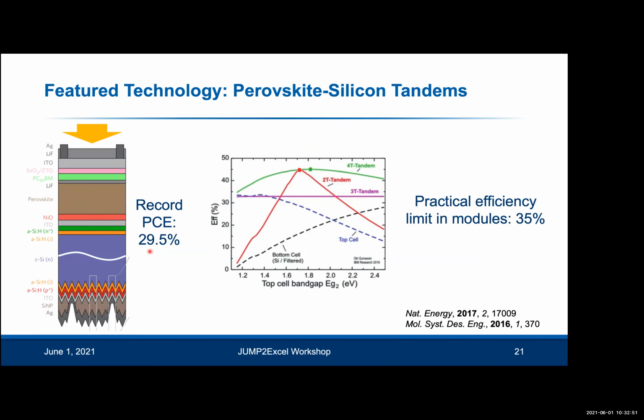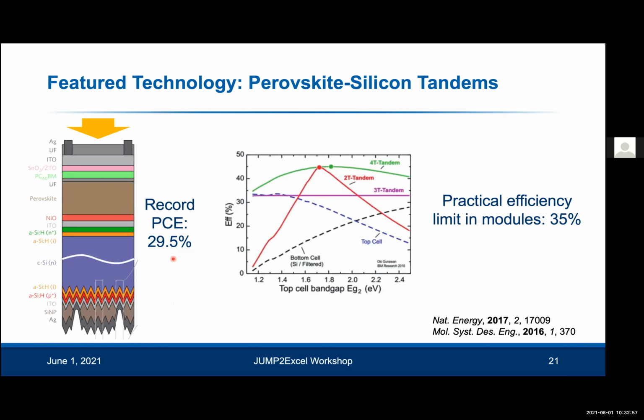And already, the record efficiency for this technology is 29.5%. And that's significant because this is greater than the efficiency limit for single junction silicon devices. Remember, the efficiency limit for single junction silicon is 29%. And this is also right at the practical limit for a perovskite single junction device. And people predict that in the future, it's realistic to make modules of perovskite silicon tandems that can reach 35% efficiency. So that is really quite exciting, which shows that you have a realistic device which can overcome the theoretical limits in efficiency for each of these individual subcells.